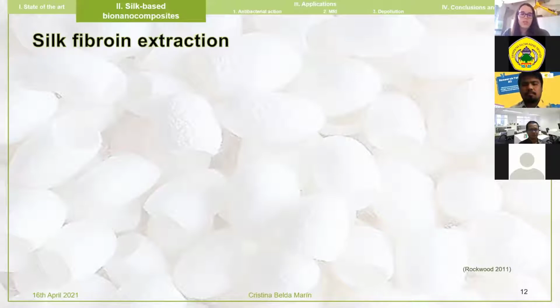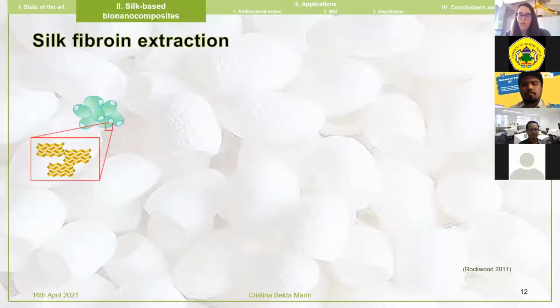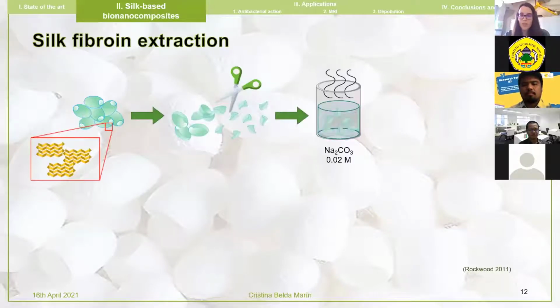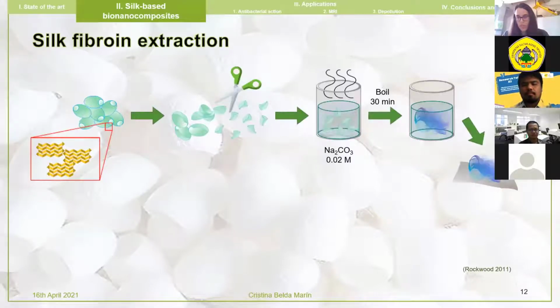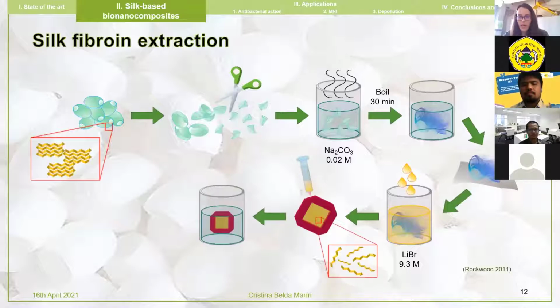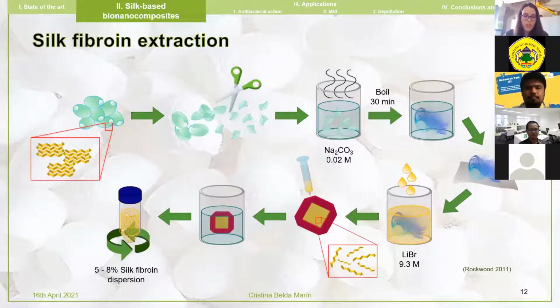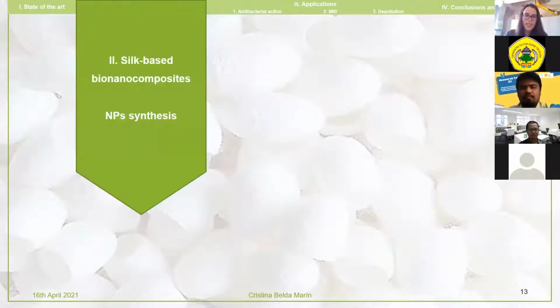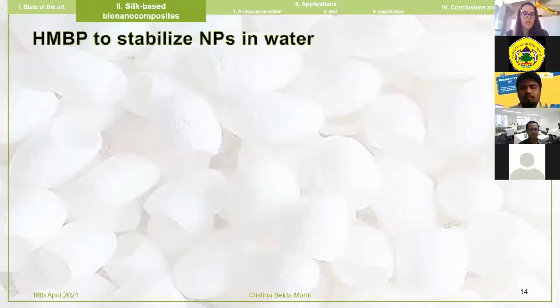We're going to explain how silk is extracted. So quickly, we get our silk cocoons, in which, I remind you, silk is structured in beta sheets. Then we cut them, we boil them, and we obtain this sort of mesh. It's then suspended into lithium bromide and then dialyzed to finally obtain our silk fibroin dispersion. This procedure has been FDA approved, so it's something that's very standard and already well known. So now the idea is to incorporate nanoparticles into this solution.